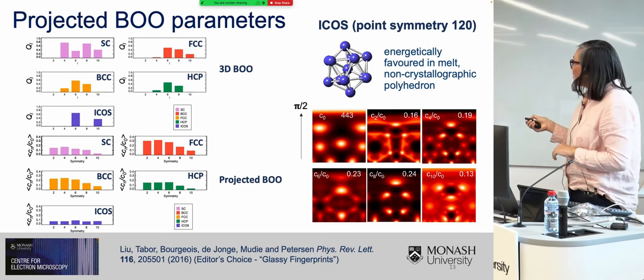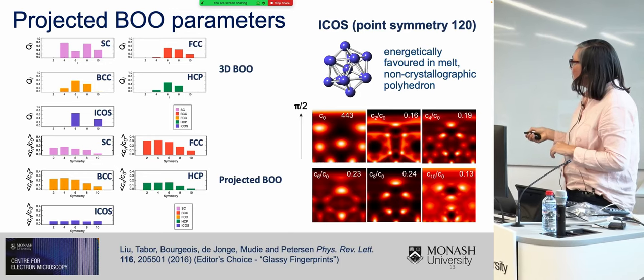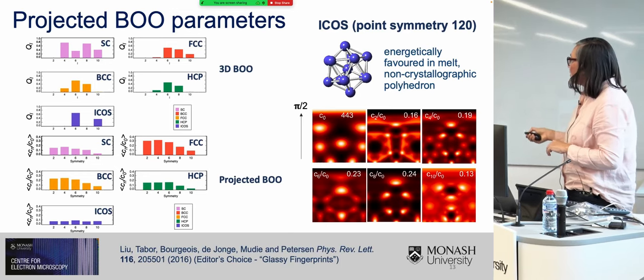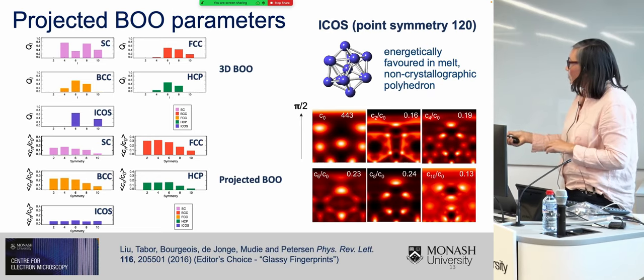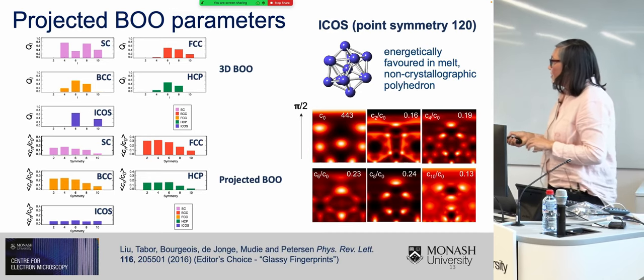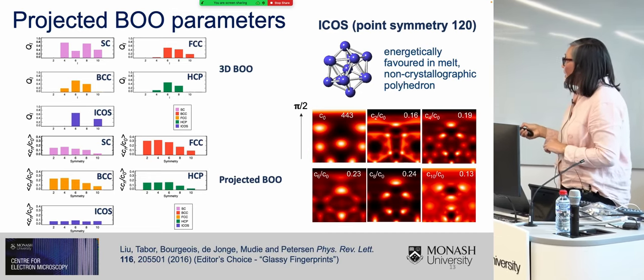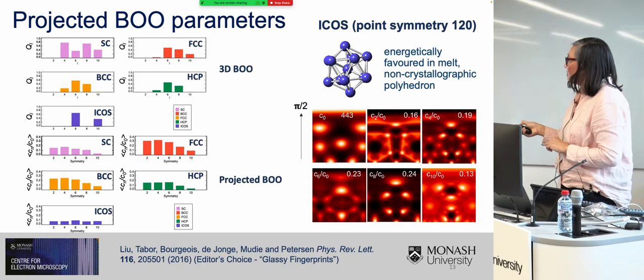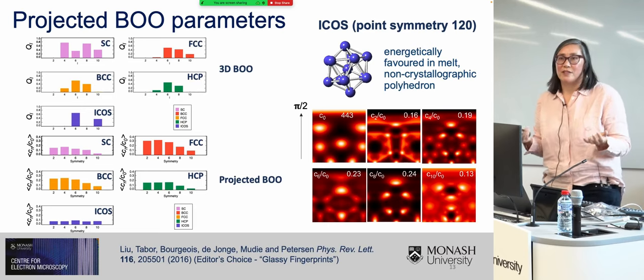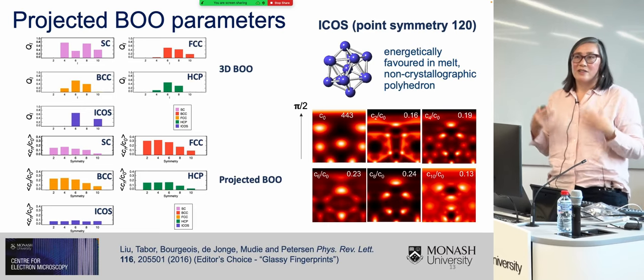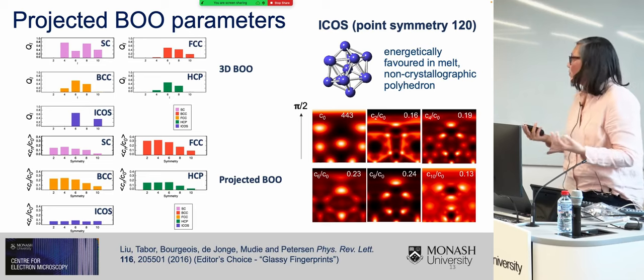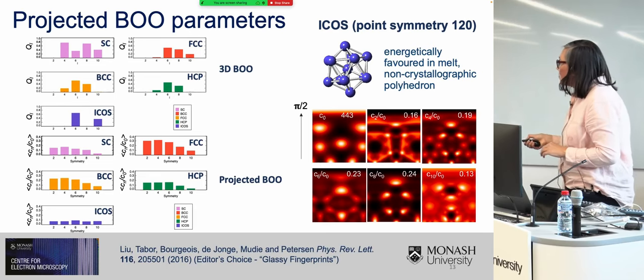So I rotated this through all possible angular orientations, and then I took these lovely, attractive, symmetric maps and averaged them to obtain my projected BOO parameters. So it's evident that compared to these three-dimensional BOO parameters, my projected BOO parameters have lost a lot of symmetry, a lot of information. They're not as strong fingerprints of local order. But you can still see that there are